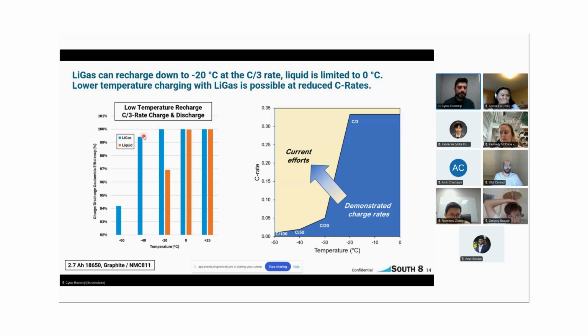Then you go to minus 40, and we do see a little bit of a drop with our LiGas electrolytes. So we cut off on our spec sheet, if you will. Minus 20 is what we can do. Minus 40 is hitting that danger zone, if you will, with our current cells and electrolytes. But you can see the liquid electrolyte just drops out completely. You get no charge or discharge with those liquid electrolytes.